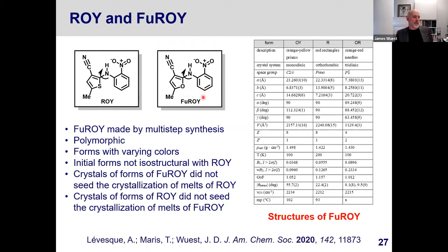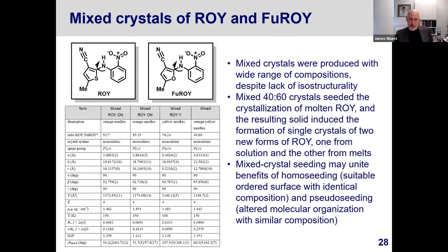we began to use these FuROY crystals to seed the crystallization of ROY by using melts of ROY. None of this worked with the initial crystals of FuROY, and conversely, using crystals of ROY to seed the crystallization of FuROY from melts was not successful. But we eventually found that the mixed crystals of these two compounds had an effect on the crystallization and led us to new crystal forms of ROY itself.